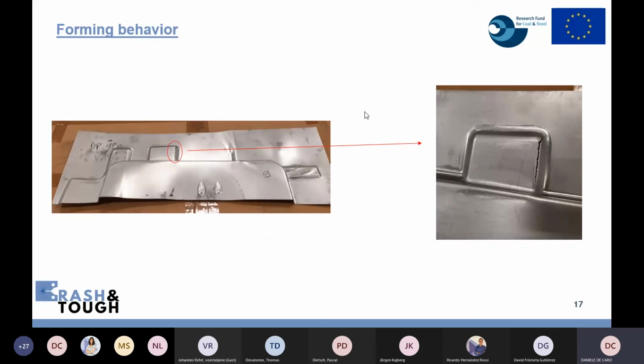And here I can show also that otherwise on dual phase 1000, so the first steel generation, the formability is effectively lower than 1180 high formable grades, and some cracks on some components occur due to too critical areas with high strain.